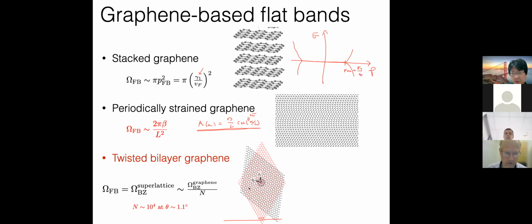In twisted bilayer graphene, it's this avoided crossing between two Dirac points, which is how I explain it. So in this sense, all these approaches have slightly different ways of explaining the size of the flat band. In twisted bilayer graphene, the flat band seems to be isolated from the other bands. In these two other cases, like in here, you kind of continue with the dispersive band. There are other bands here. So this is kind of isolated, but it is not an entirely flat band everywhere. And in this case, it's basically just something like this. For 1D strain, the dependence on kx and ky is completely different. As a function of ky, it looks like this in this case.